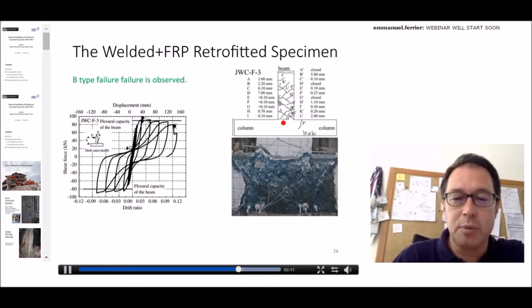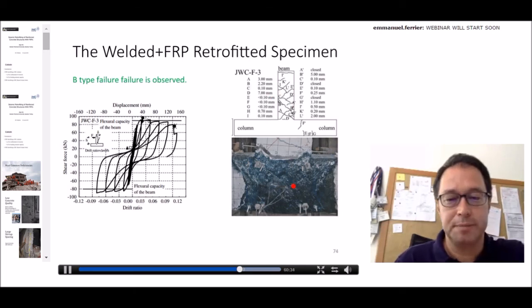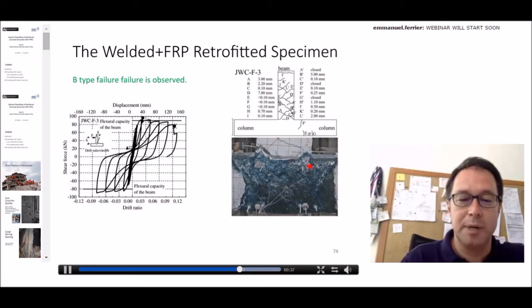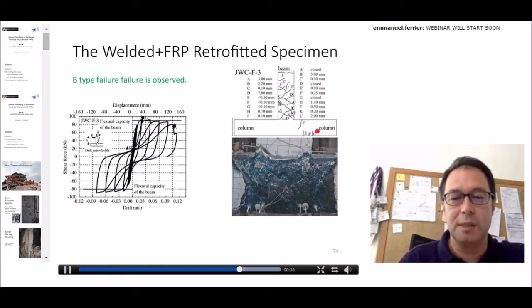We had damages within the beam because this was the target. If you wanted to eliminate this type of failure, you could retrofit this part as well. But often that's what we want. That's a desirable failure mechanism. We want the damages to occur within the beam to survive the earthquake, to dissipate the energy. And this is what happened in the case of this specimen. There are some slight damages on the column as well. But since the column was stronger than the beam, in this example, we didn't experience any serious problem. If the column is weaker than the beam, of course, you should also retrofit the column as well.